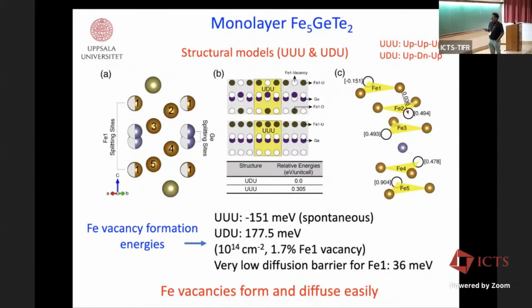And we have also calculated the vacancy diffusion barrier. You can see that the diffusion barrier for iron 1 here is actually very small, only 36 milli-electron volt. That means when the iron atoms are removed from the UUU structure, they can diffuse very easily and go somewhere else. So that makes the system rather complicated.